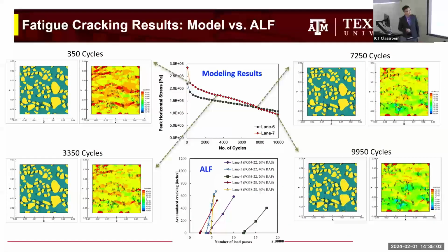That will be linked together in two-way coupling. Then we can see different levels of progression of the damage, from 350 cycles to about 10,000 cycles, progressively growing damage at different locations of the loading cycles. We simply compare lane 6 and lane 7. It takes a lot of time for simulation, by the way. The two lane cases are 6 and 7, and here is the ALF data to be compared. Lane 7 is worse than 6, and that was captured by the ALF data too. So this indicates the validity of the concept, but we still need some more validation to be done, and it's coming up.